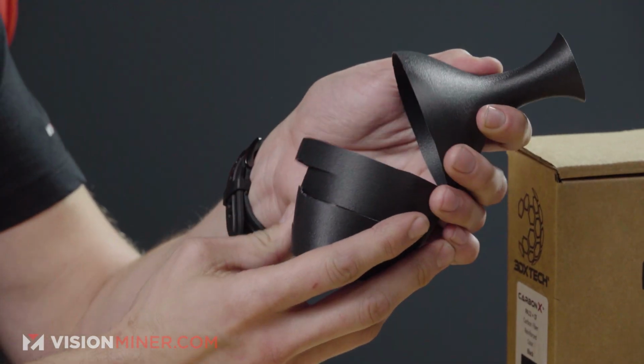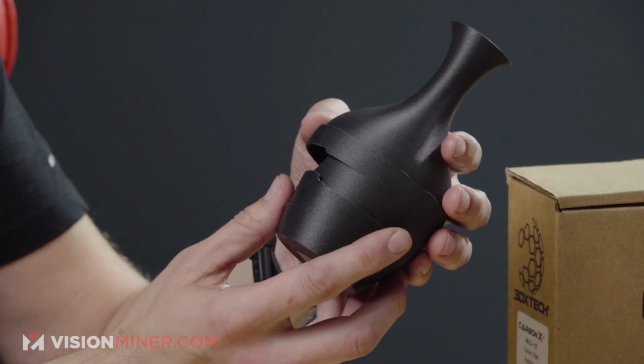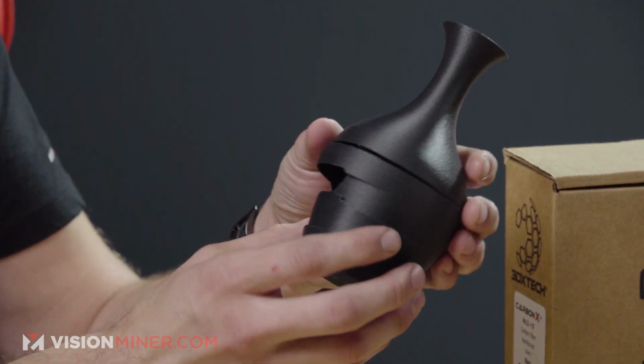Now this is to be expected for almost every FDM material. There are a couple out there now that don't do this, like PCTG, which is an insane material. Definitely check that out. But this is interesting. It doesn't break as quick as some other materials like PLA would, but it still is a bit more brittle and not quite as good Z-axis adhesion on super thin walls as, for example, CFPA6 or HTN. So I'll put that to the side right there.